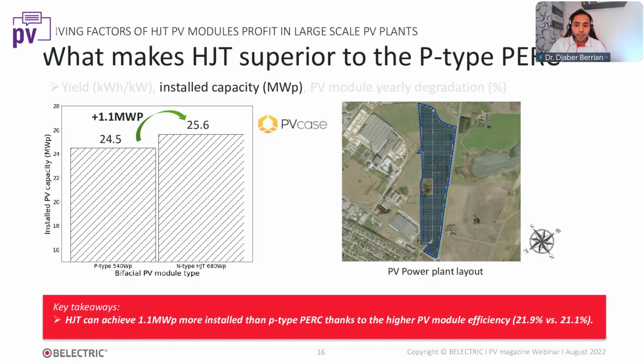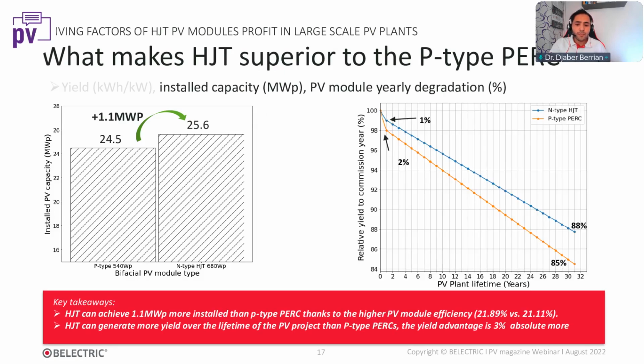The second factor we found, what you see here on the right-hand side, is the layout. If we use this layout with the P-type PERC module and with heterojunction, we see there is a gain in installed capacity. So a gain of 1.1 megawatt peak more if you use the heterojunction PV module, and this is thanks to the efficiency of heterojunction. And the last factor is the degradation, which is very important.